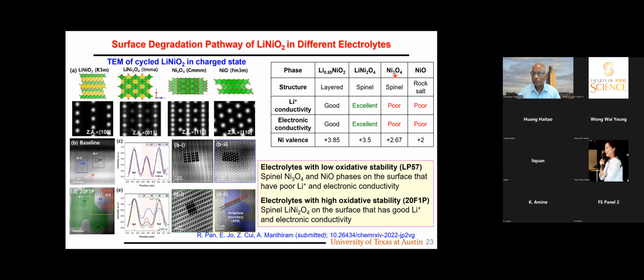In Ni3O4, you have nickel ions in the tetrahedral site, which is really bad, a poor lithium-ion conductor, and it is a reasonably poor electronic conductor as well. Nickel oxide, I do not have to explain, both of them are bad. So this is why the surface reactivity, what is formed on the surface, good electrolyte versus bad electrolyte, stable electrolyte versus unstable electrolyte, makes a big difference.